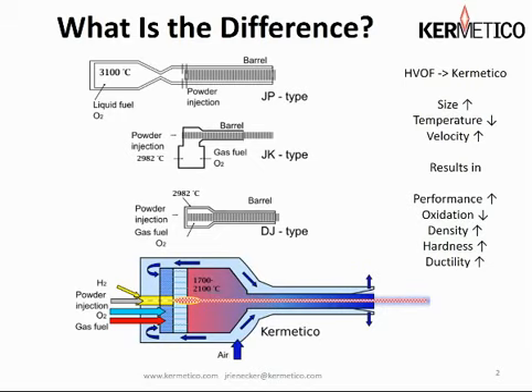Next up, we have a JK-type gun, and here, although the powder injection is axial, the combustion chamber is 90 degrees to the line of flight for the powder and the barrel. Do you think these gases, when they make this 90-degree turn, will not interfere with the powder stream? I find that very hard to believe. I think the powder stream is going to be disturbed, and the reason for the shorter nozzle here is because anything much longer would result in powder buildup on the inside of the nozzle.